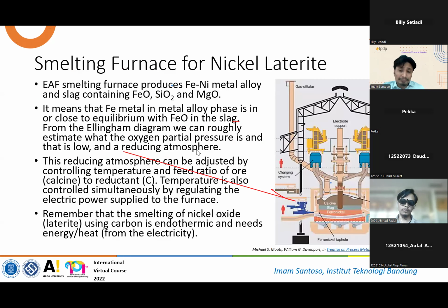It depends. In the electric furnace, you can control the temperature by adjusting the electrical voltage. For example, you can control the arcs here, the trafo. What is the kV of the trafo? You can control the temperature with that in an electric arc furnace. In the copper smelting process, you can control the temperature through the ratio of concentrate and the oxygen you introduce.